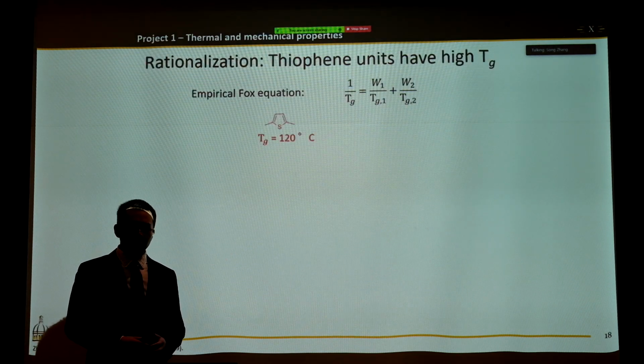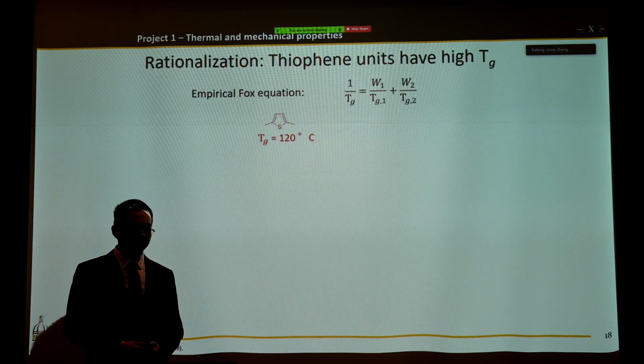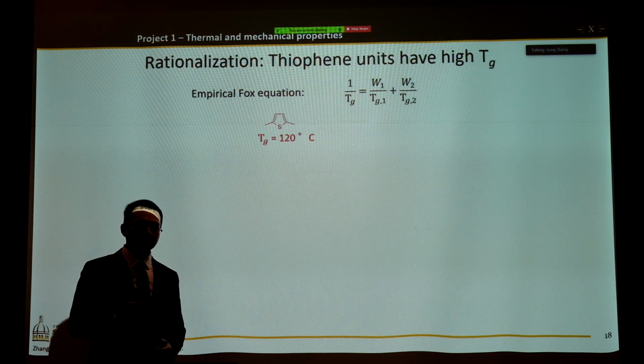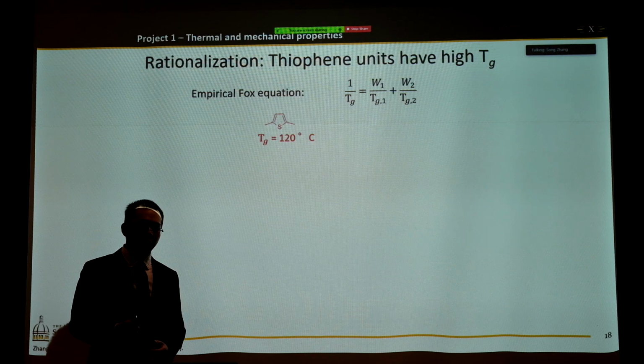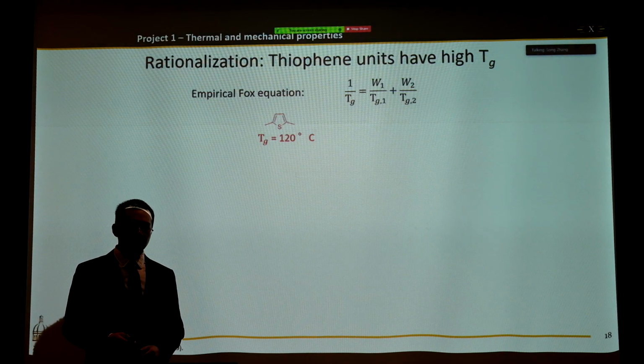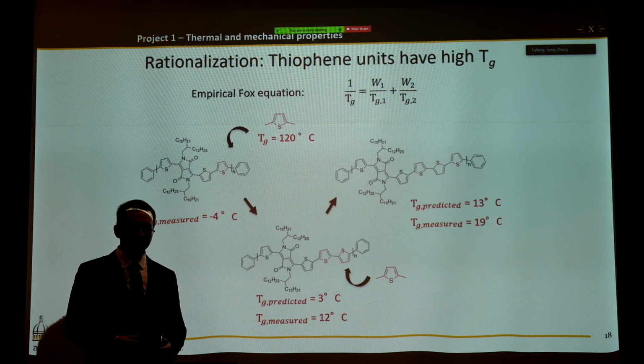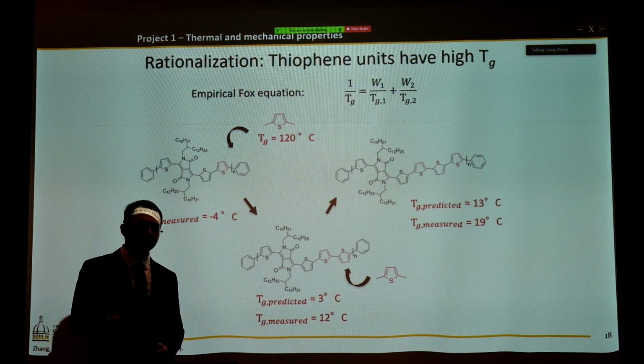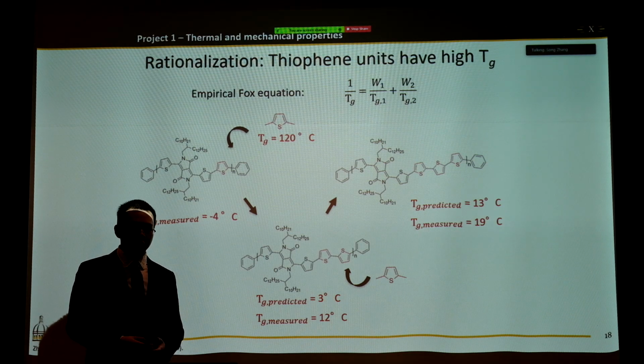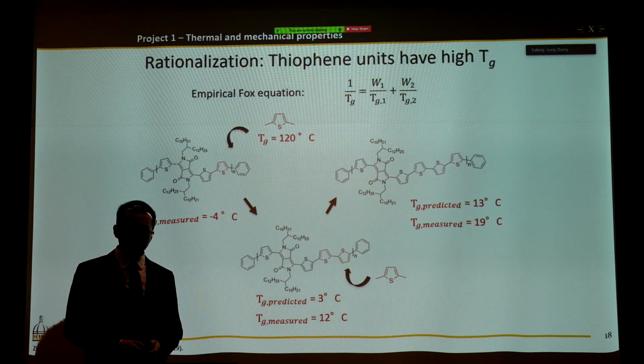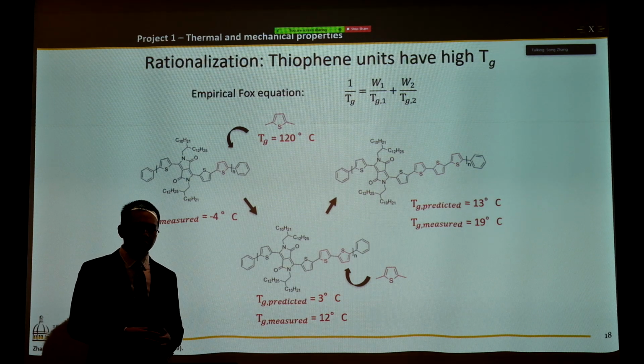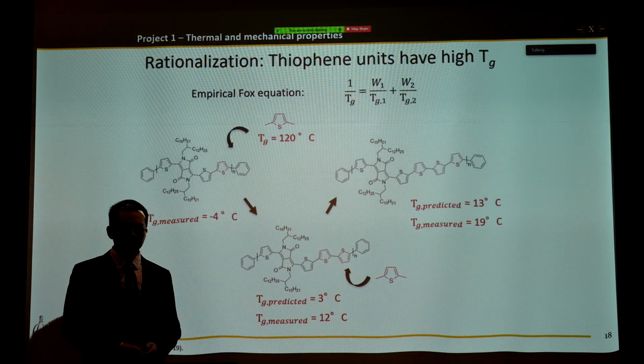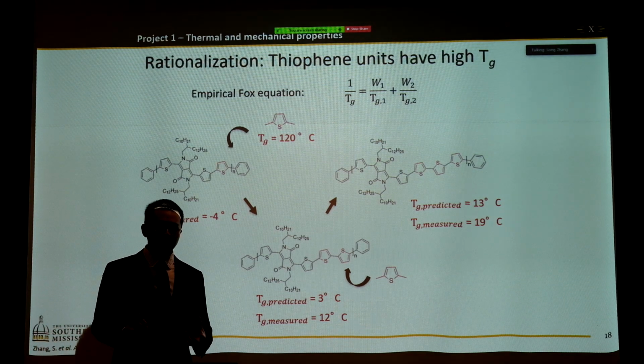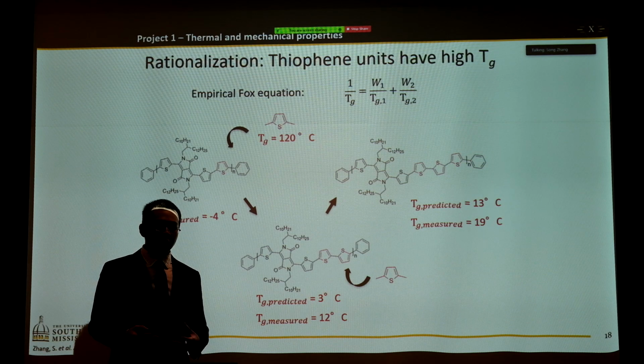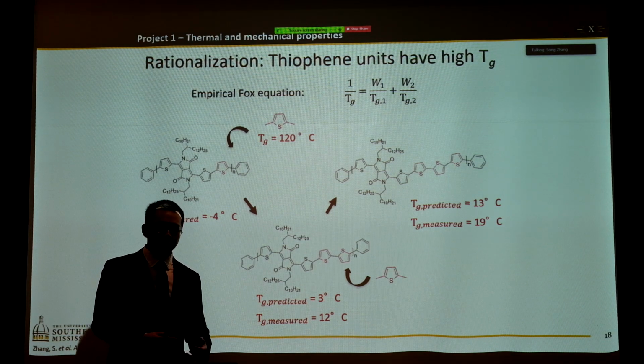It turns out it should be pretty easy if we just use the Fox equation. In the literature, people reported that unsubstituted polythiophene has a Tg around 120 Celsius degrees. So just imagine you put that into a low-Tg polymer, of course the Tg is going to increase. And the predicted Tg is actually similar to the measured Tg. Now, how do we understand the low Tg for the DPPT polymer, which is around -4 degrees Celsius? Well, we know the high-Tg thiophene is increasing the Tg, so the low-Tg component must be dropping the glass transition. So it has to be the side chain effect.